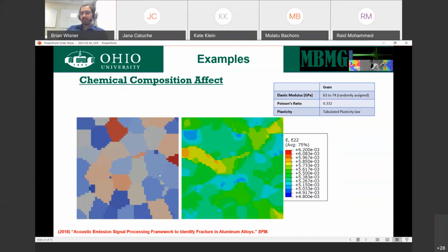Can we do so considering the fact that in reality, a particle does not usually sit just in a single grain? Many times they're on boundaries. And this is just a quick simulation to show you the concept that if we take a grain structure with different crystal orientations and we strain it, the stress and the strain is not going to evolve uniformly. It's going to concentrate in the different grains because of the preferential orientation. Given all of this information, we want to be able to detect that these kinds of things are happening at this scale if we want to be able to control them.